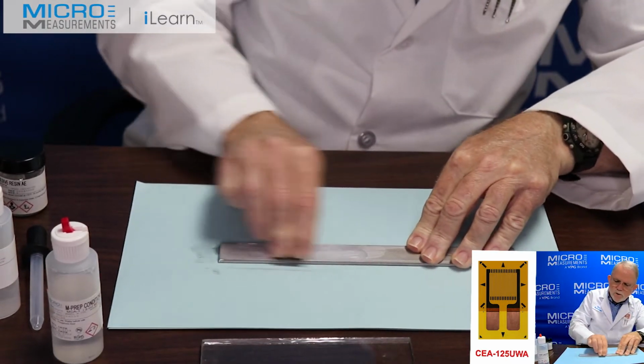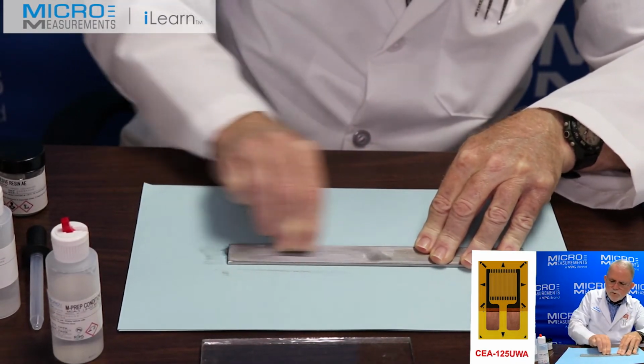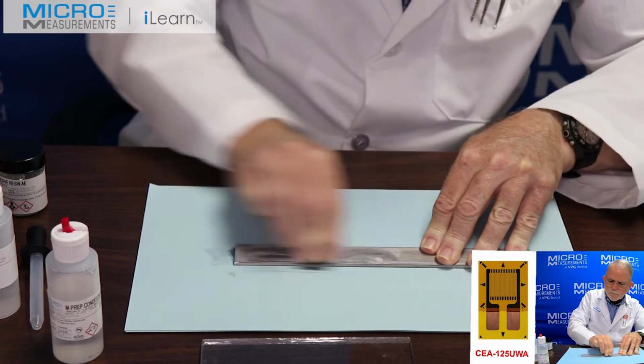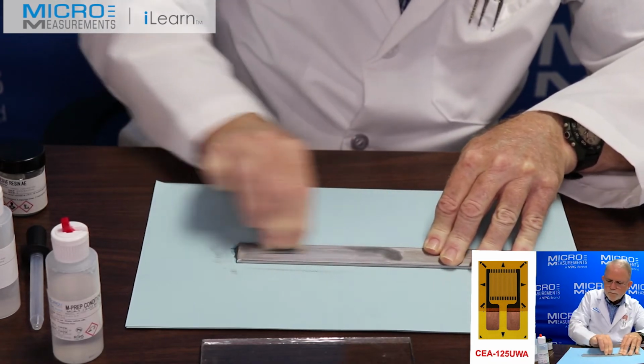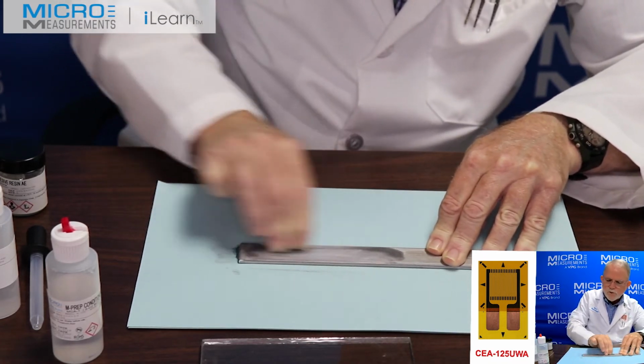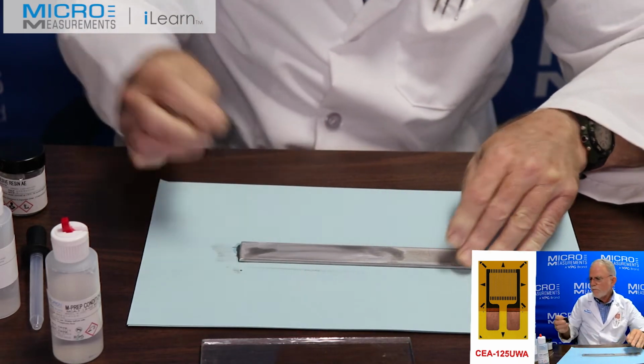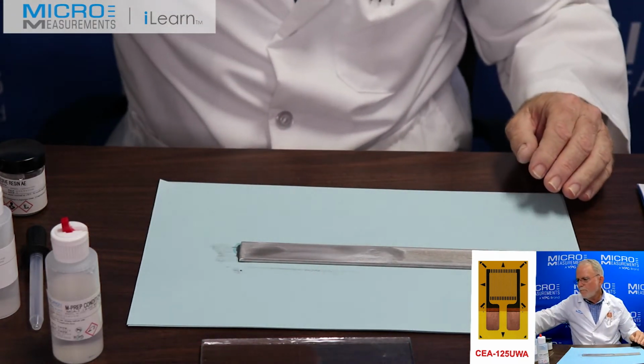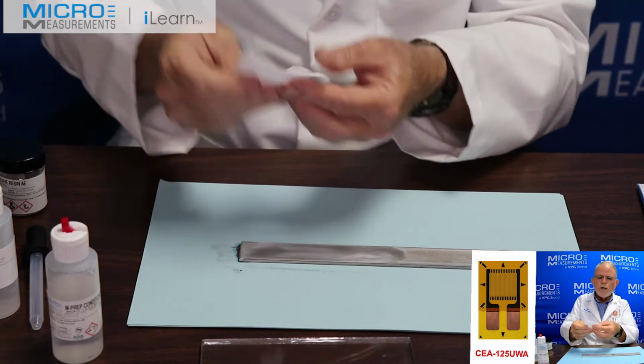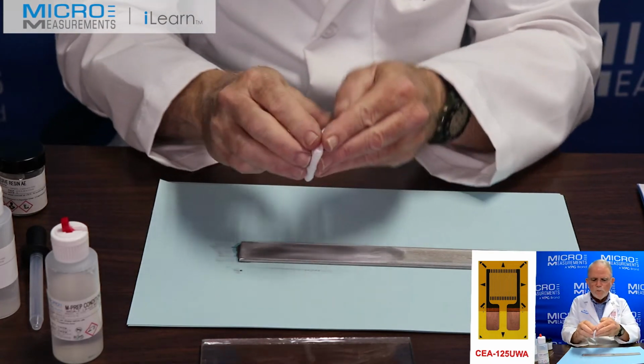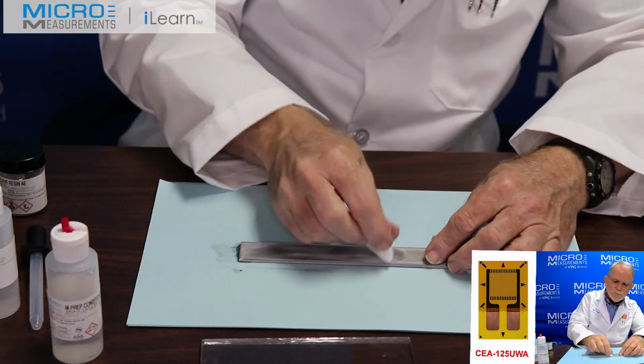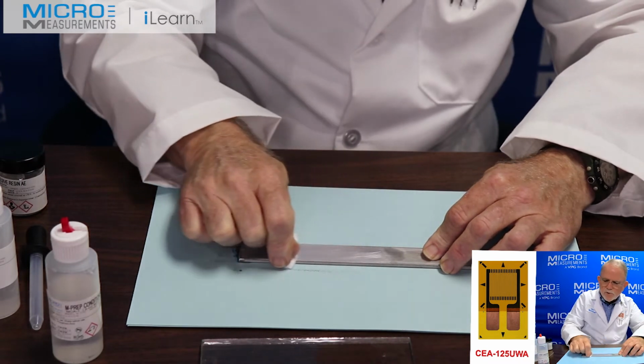And I'm going to wet abrade with the 400 grit. Ten or 12 strokes. And another clean, dry gauze sponge, I'm going to absorb that material off the beam. It's the contaminated material, the conditioner A.